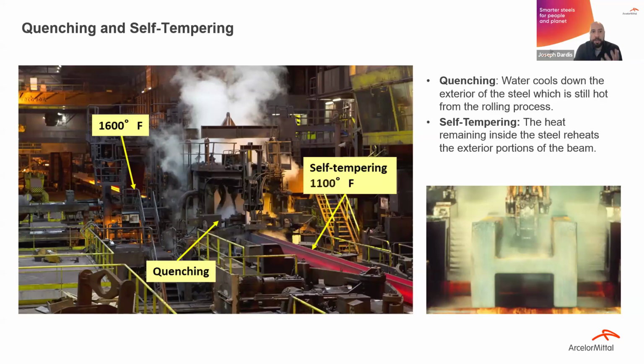Then you'll see it enter a QST, or quenching and self-tempering bank, where it's rapidly quenched along all of its perimeter. You can see on the right, there's a cross section where that's happening. So what's happening there is, as you're quenching it, you're rapidly cooling that section, and that's refining the grain of that piece of steel. And that refined grain increases your yield strength significantly. But you don't quench it all the way through the cross section. You still leave that core, kind of in the inner portion of that steel hot.